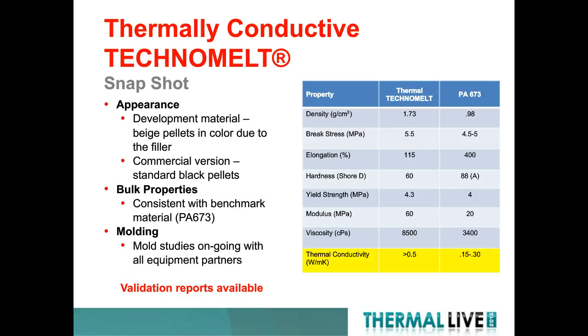The material is relatively harder given that the filler has been introduced, but still provides a very good yield strength. And the modulus itself is increased, but not by a factor of 10, which is typically where in the materials world we start to consider fundamental differences between the behavior of materials. And the viscosity itself at melt temperature is less than 10,000 centipoise, which allows it to be moldable.